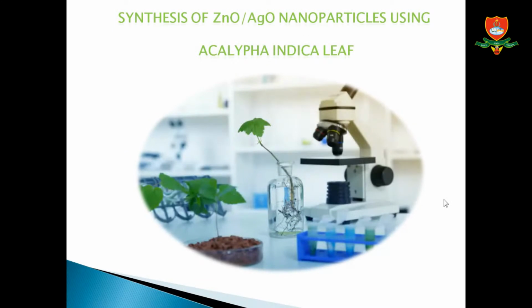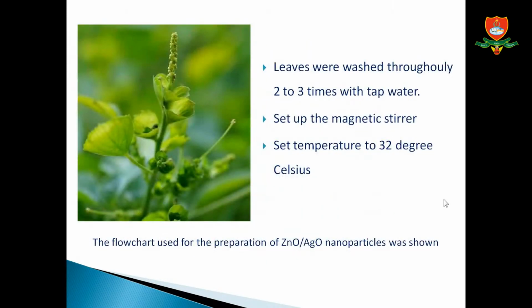Synthesis of zinc oxide and silver oxide nanoparticles using Acalypha indica leaf. The green route for nanoparticle synthesis is chosen due to its eco-friendliness, economic prospects, and feasibility. The leaves were washed thoroughly 2 to 3 times with tap water, and then the magnetic stirrer was set up and the temperature set to 32 degrees Celsius.